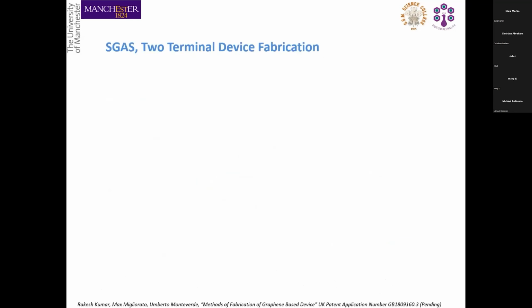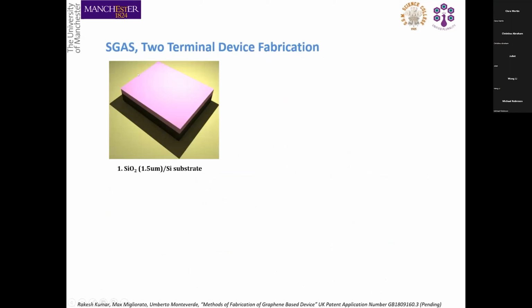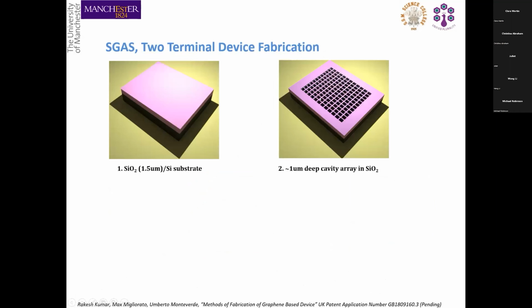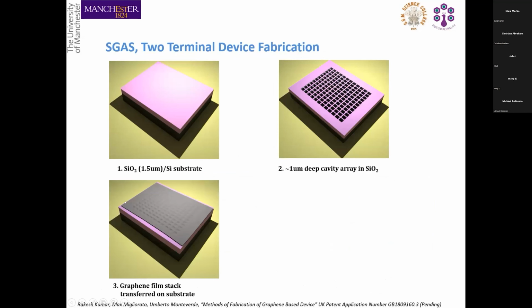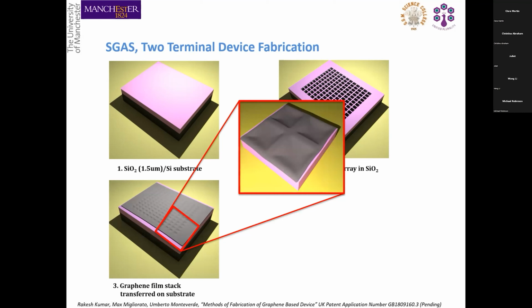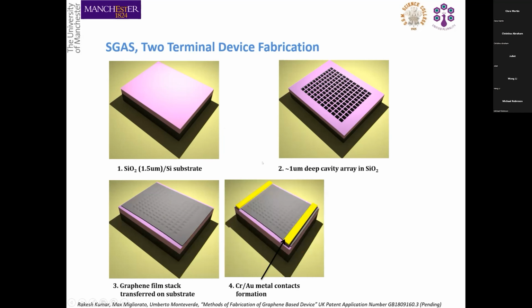So the simplest way of making such devices: you start with the silicon oxide substrate, and then you create cavities through an RIE system, a dry etching system, and then you transfer the graphene film stack. This graphene film stack comprises graphene underneath with a polymer, which is lithographically patternable, and then there's a metal film on it that provides some strength to the polymer. Otherwise, the polymer breaks. So it's slightly different from the traditional method of transferring graphene with PMMA. This is how it looks when it goes onto the cavity. So it sags a bit. That's why we need to keep the depth of the cavities around 1 micron, where the sag can be up to 150 to 200 nanometers. So it doesn't touch the surface.